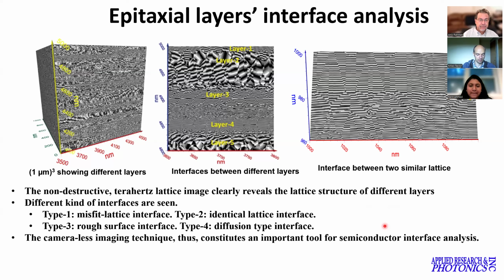Interface is the space between the two surfaces. And ideally, what we want is that they should form a very integral interface, no impurities, no defects, no crack or delamination. Those are the kinds of things that need to be inspected, because if they are there, then the device will not work properly, or they will fail very quickly.